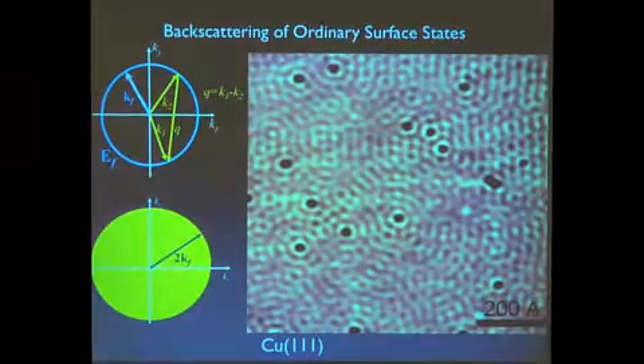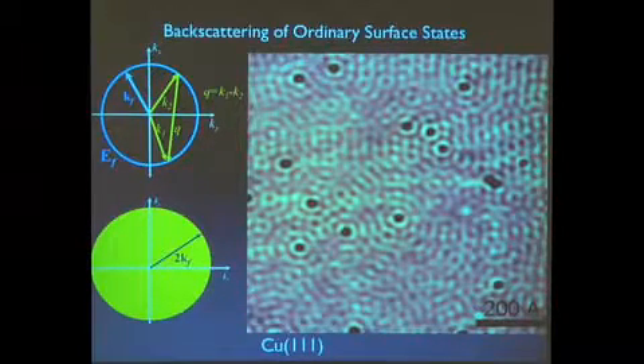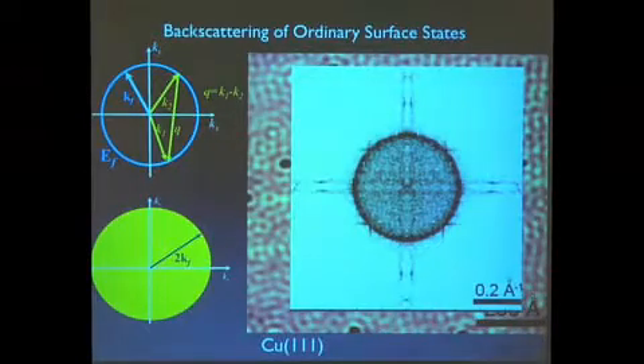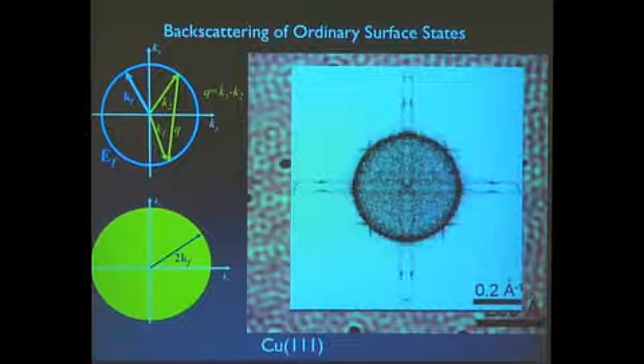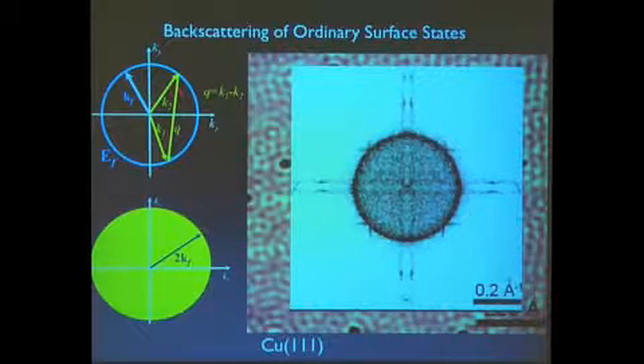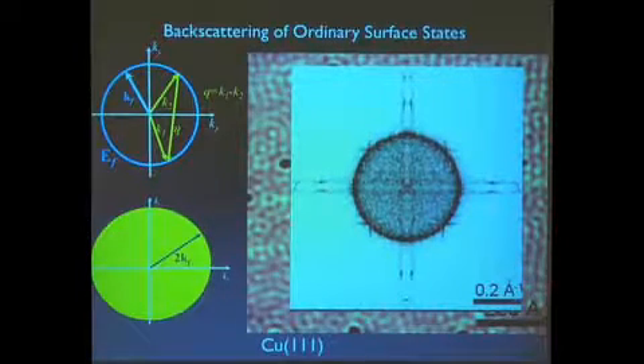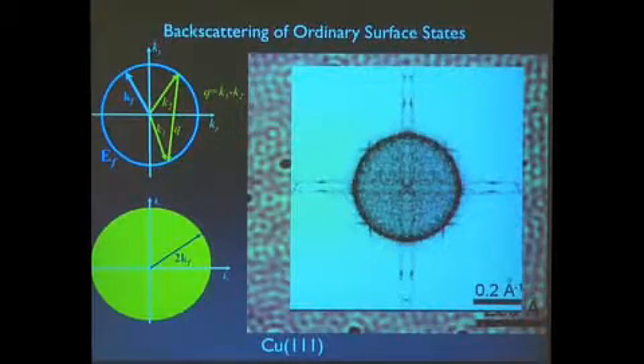So let me show you such a map just looking at an ordinary surface electronic state. This is on a piece of copper. What you're looking at is a piece of copper intentionally basically dosed with a few CO molecules, which appear as dark dots here. And what you're looking at is basically standing wave of electrons scattering from defects. Essentially, what you're looking at is the process of backscattering. So if I took a Fourier transform of that image, essentially it shows you that if you're living on a circular Fermi surface of the copper 111 electrons, which is pretty much a free electron gas, you basically are exploring equally this entire Fermi surface. And if I change the energy, this circle basically changes size, giving you a way to also map this Fermi surface. But most importantly, what it's telling you about is about the allowed scattering in the problem.